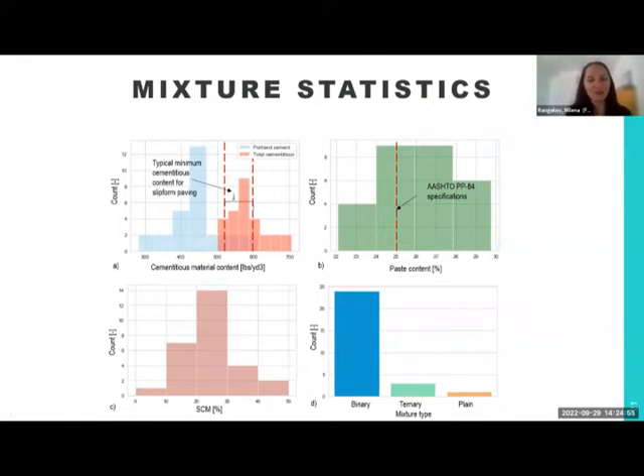So in this slide, I'm showing mixture statistics based on what MCTC has collected. In this first graph, graph A, the red portion shows total cementitious contents, and we can see these lines that are kind of bracketing typical slip-form paving specifications. What we have seen very early on from this data set is that our total cementitious content is a little bit on a higher end of what is typically specified. So we are using a little more powder than we probably should.